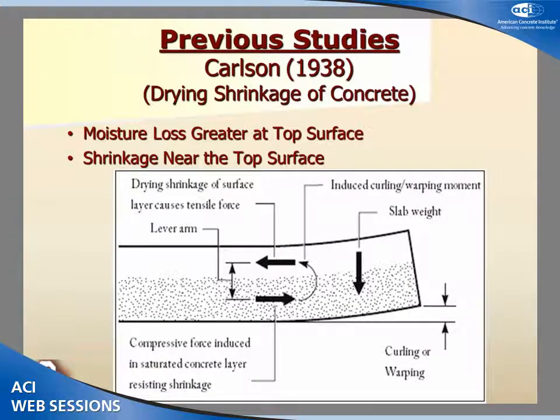Now I'm going to review some of the prior research in this area. In 1938, Carlson performed an experimental study on drying shrinkage of concrete. He studied 3 types of cement and 2 types of aggregate, and he showed that the moisture loss is greater at the top surface of the concrete, and also that shrinkage occurs near the top surface. So he concluded that when moisture loss occurs at the top surface of the concrete, a moisture gradient develops through the depth of the slabs, the moisture gradient causes a shrinkage gradient, and the shrinkage gradient applies a curling or warping moment into the slabs.